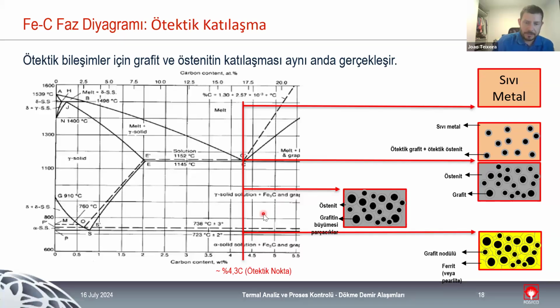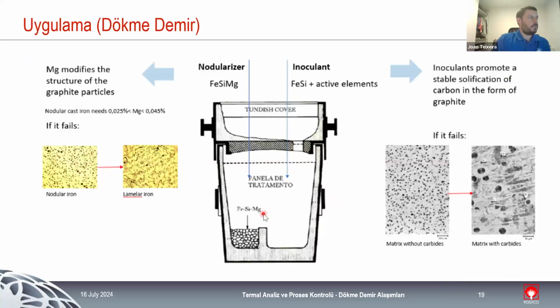If we are dealing with compact and nodular, we are going to add magnesium to change the shape of the graphite. But whether we are dealing with gray, compact, or nodular, we are going to add inoculants to try to promote the transformation of carbon into graphite. So we have both treatments happening. Ferrosilicon magnesium modifies the structure of the graphite particles, to go from gray to compact to nodular based on the amount of magnesium that they are going to add, and inoculant with active elements promotes a stable solidification of carbon.